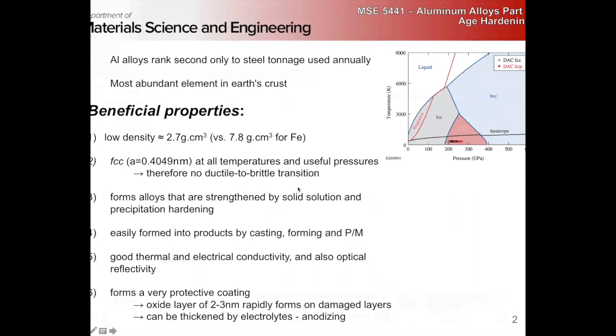Okay, so I say that we are FCC at all temperatures and useful pressures, right? So we don't have a ductile to brittle transition like we do in steels. And if we look at the phase diagram, we can see that at room temperature at about 200 gigapascals, we go to HCP. We go from FCC to HCP.